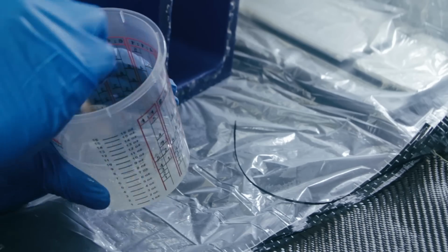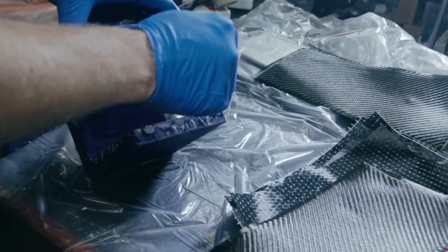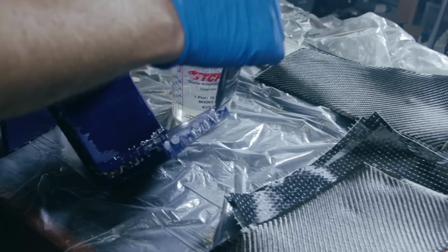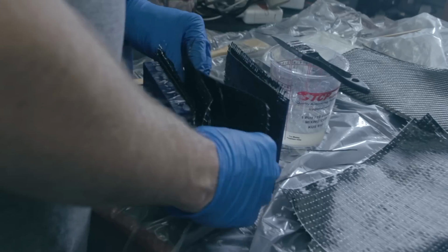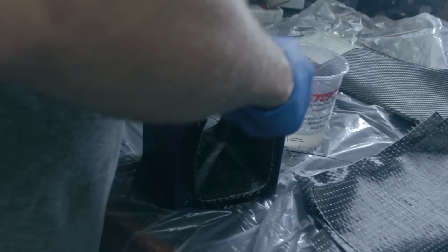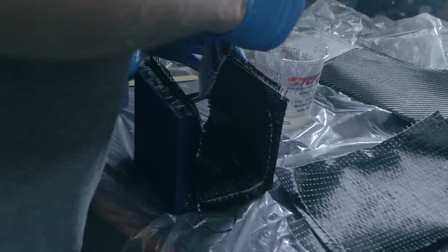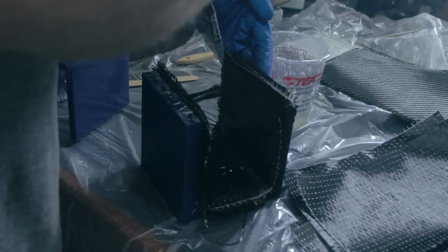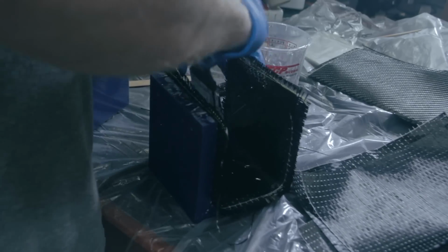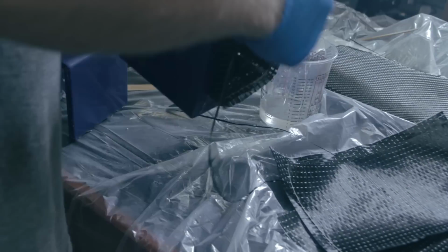Then it was time for the layup, which first involved coating the mold in epoxy, then laying a sheet of fiber, and then continuing through the layers. Things were starting off well enough, so I'm using Total Boat 2:1 medium epoxy, and my pot life should have been about 25 minutes. However, my shop that day was a steamy 92 degrees Fahrenheit.